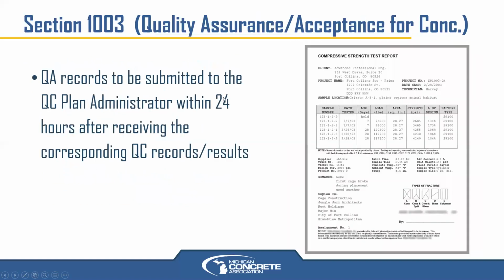One thing that we advocated for is that it's always been that QC test results have to be submitted to the engineer, the QA personnel within, I believe, 24 hours. Well, we wanted that information flow to occur the other direction as well. So we advocated that the QA results, as soon as they have them, also be submitted within 24 hours. And so then they made that contingent on when they receive the QC results, they have to submit the QA test results back within 24 hours. So if they have fresh concrete results, the concrete producer or prime contractor or concrete sub is not waiting more than 48 hours to get relatively real-time results from the other side of the testing, so that they can compare QC and QA results prior to identifying a problem at 28 days.